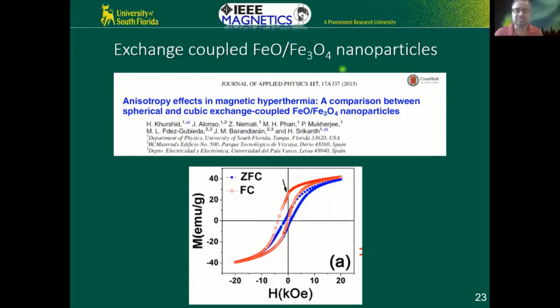So it has to be magnetite. So magnetite is the shell. So it's sort of an inverse core shell approach. The core is actually antiferromagnetic and the shell is ordered, okay? Usually it's the other way around. When you take magnetic nanoparticles, the core is ordered and the shell is disordered, you know, because of the spin disorder at the surface. Here, it's the other way around. It's an inverse core shell.